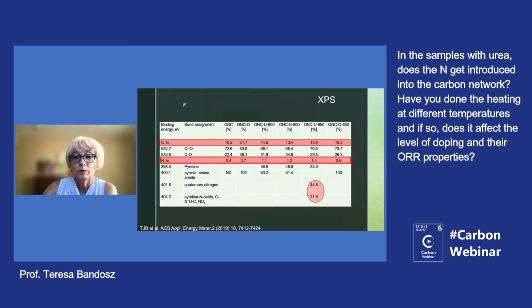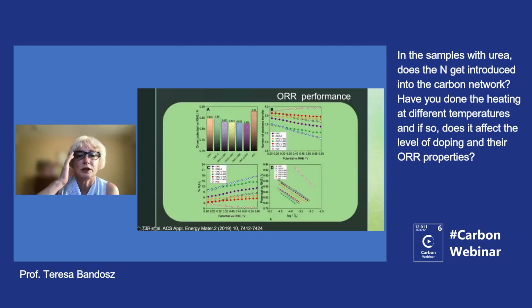And if I go back, and the performance, okay, so here we introduce nitrogen, onset potential was worse, and in the case of the number of electron transfer, only the sample which was heated at 950 was really good, and it is this sample. And then it was, of course, the sample at 600. So the problem with number of electron transfer, as I mentioned, is that in some cases the results are really close to 4, okay, for all carbons which have micropores.